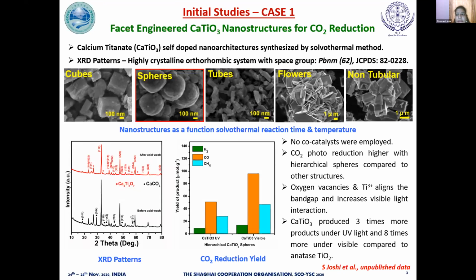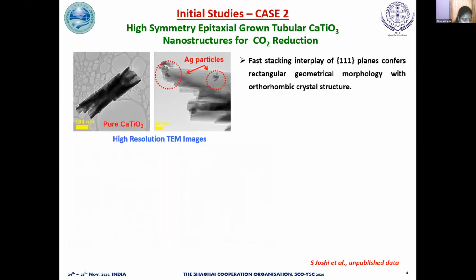Based on these encouraging results, we further developed a different chemical strategy wherein we used high symmetry epitaxially grown tubular calcium titanate nanostructures for photocatalytic CO2 reduction. A careful observation of XRD and TEM studies reveals fast stacking interplay of {111} planes confers rectangular shape with orthorhombic crystal structure.